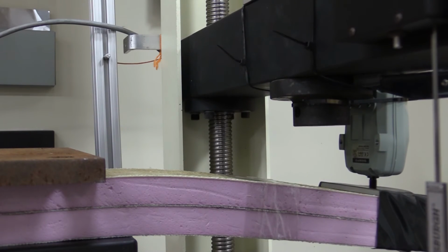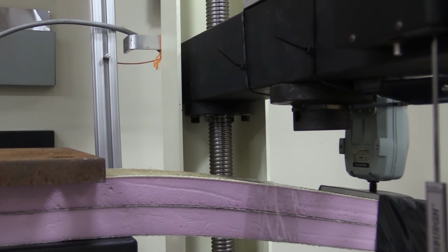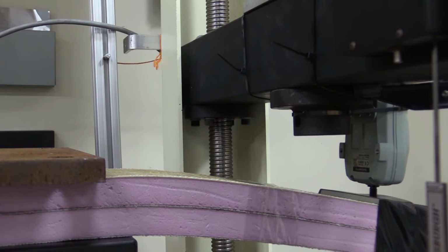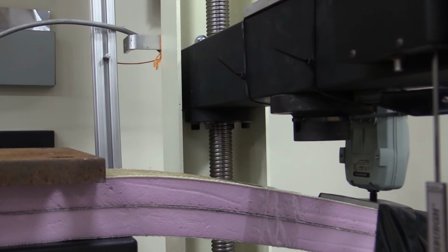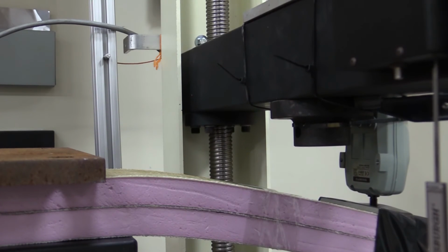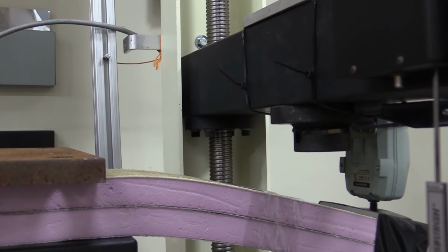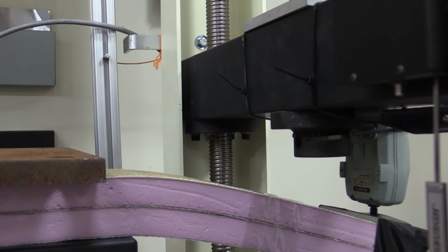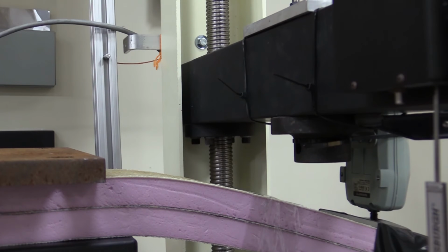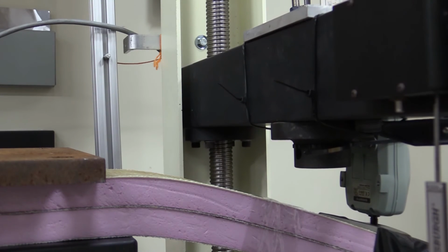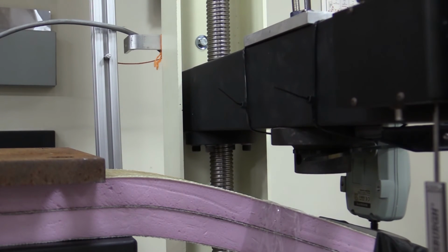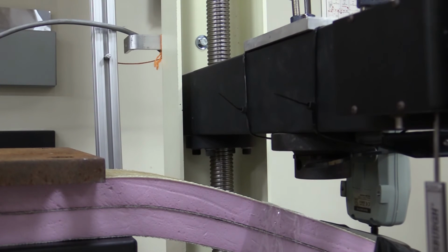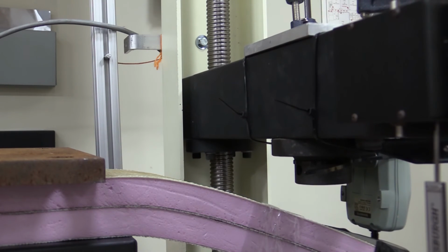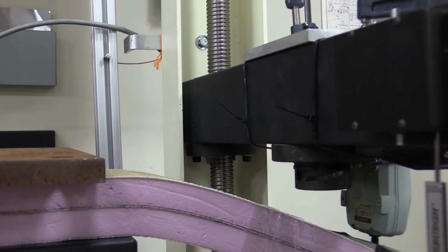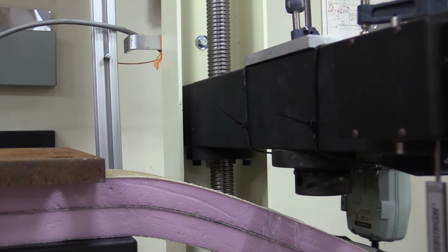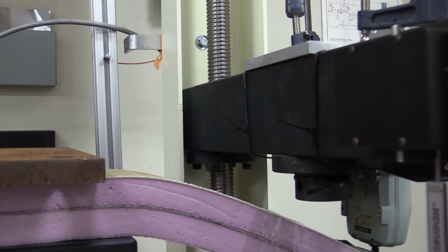We think we got enough data between the normal foam test and the sandwich composite beam, which was just the 2 layers of fiberglass on the outer edges of the foam, to conclude that for a given load, the composite beam certainly helped to prevent deflection as compared to the normal foam beam. The 3-layer beam was pretty much a failure since it sheared almost immediately.